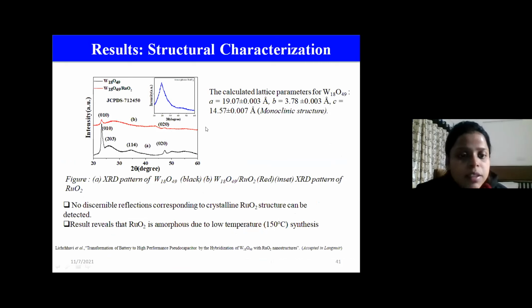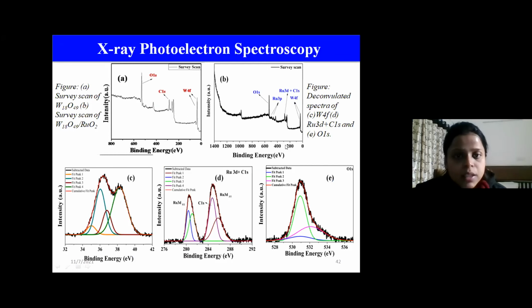So this is the XRD, and we can see that this is for the W18O49, and this is for the hybrid nanomaterial, and we can see that amorphous ruthenium oxide has been formed by suppressing the 010 peak of the W18O49 nanomaterial. This is the XPS characterization to confirm the W18O49 and the presence of oxygen vacancies, then the Ru 3d states, and then the W5+ and W6+ oxidation states.